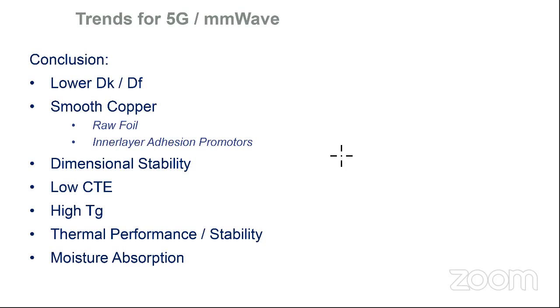We've embraced spread glass as an industry, and we all know it's part of the material set, but certainly the spread glass has given us a lot of benefit that we don't talk a lot about, and that is the signal integrity over the surface of a substrate. The resin to glass ratio or presence is more equal, so you don't get the interruption of resin-rich to glass-rich locations across a field. So that's going to be a factor of our glass selection and style.